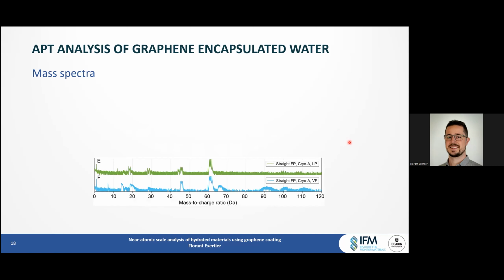And then for the cryo scenarios, the first point to note is a slightly better yield compared to the room temperature scenarios on that instrument. And the second point is that although some frost could be seen at the tip of the specimens, the samples could be analyzed regardless, and there are noticeably fewer peaks than for the room temperature experiments.